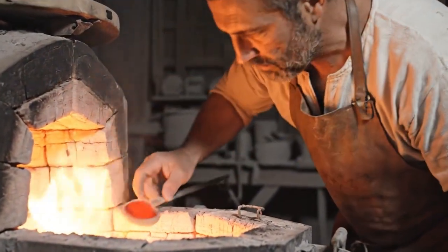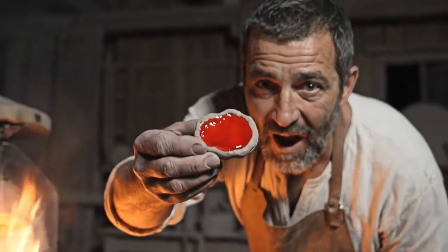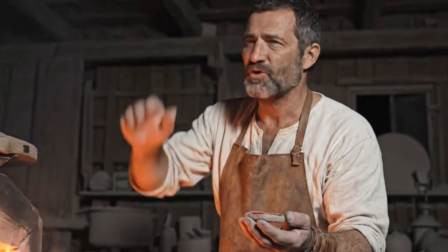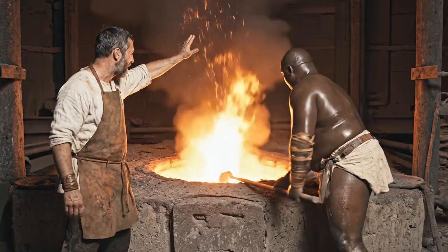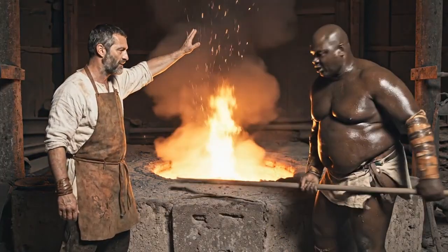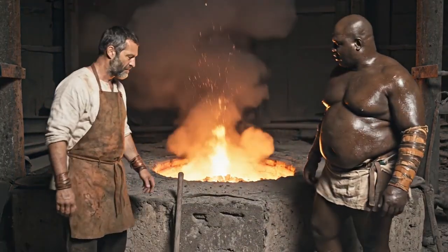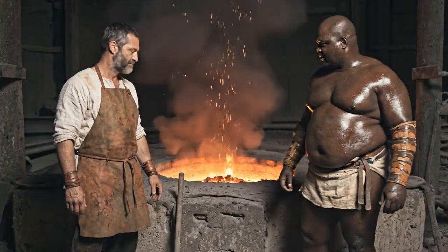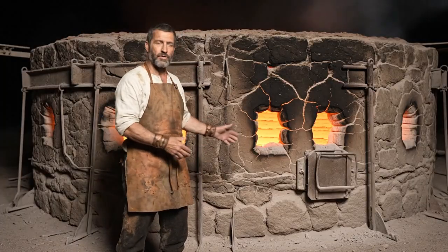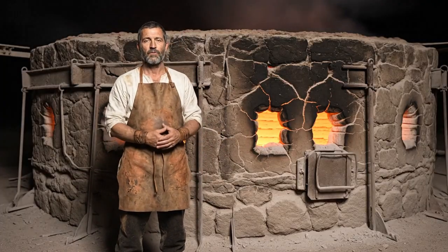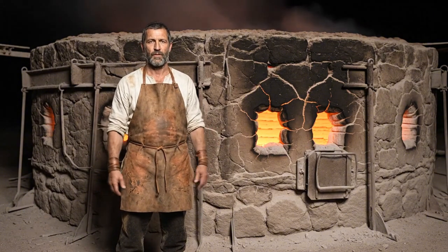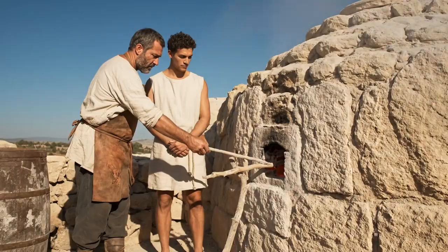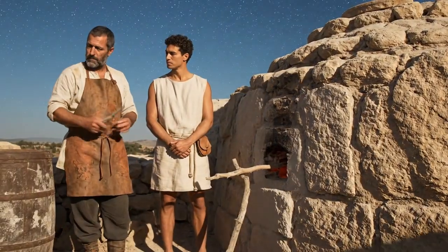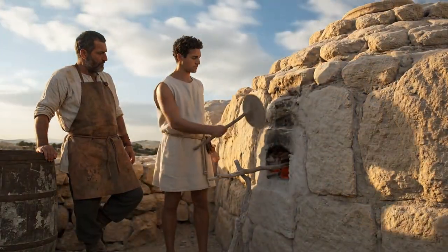When the master potter judges the temperature correct, the slip on the test piece has turned from chalky pink to glossy, saturated red. The stoking ceases, and the kiln is left to cool. This cooling phase is itself critical. A too rapid drop in temperature will crack vessels by thermal shock. A kiln this massive retains heat for days, and patience is not a virtue, but a structural necessity.